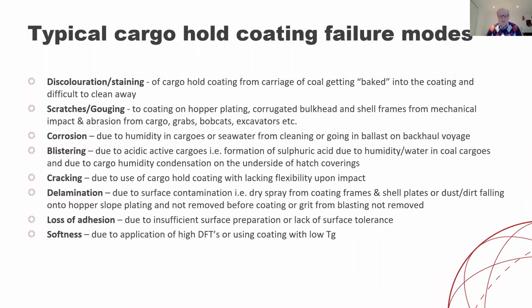You can have cracking if you are using a coating that doesn't have sufficient flexibility upon impact. You can have delamination, of course. It could be surface contamination from dry spray when you are applying it, on a new build or maintenance, or it could be when you are using some kind of cosmetic coating. And loss of adhesion, typically from insufficient surface pretreatment or lack of surface tolerance of the cargo hold coating that you are using. And then softness due to application of high dry film thicknesses or using a coating with low Tg, glass transition temperature. That means the coating is not hard enough to carry warm cargoes.